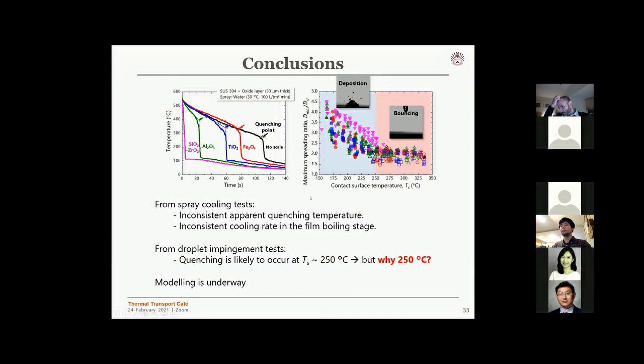And to see why this happens, we did a droplet impinging test, and we found that quenching might occur at a surface contact temperature of around 250 degrees Celsius. But the question remains, why 250? And that's something we have been working on right now. But if you have any idea, please share with us.